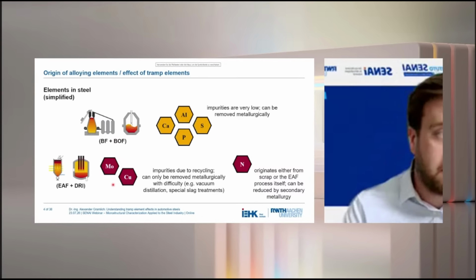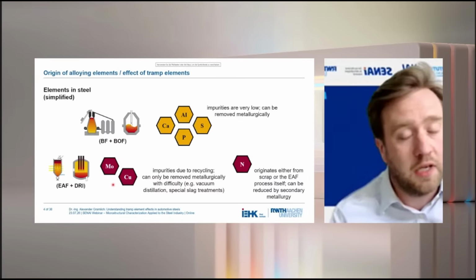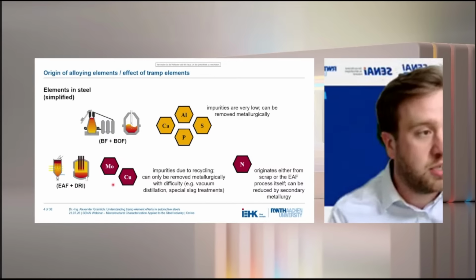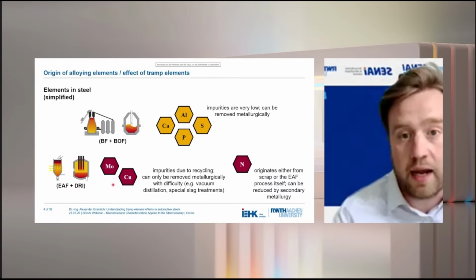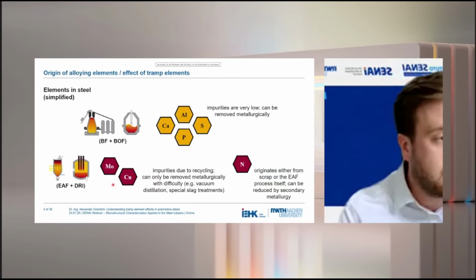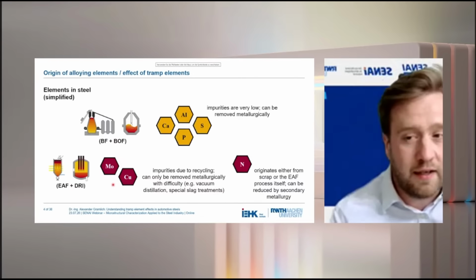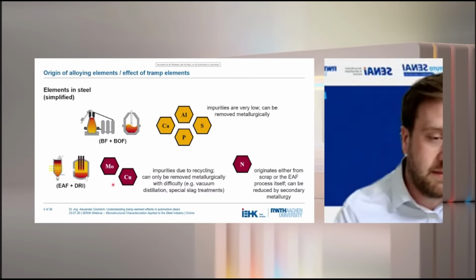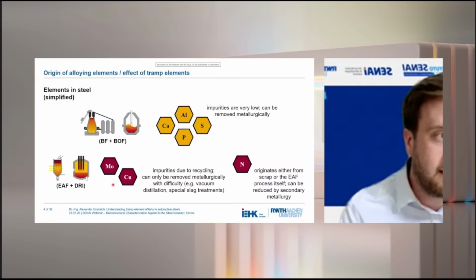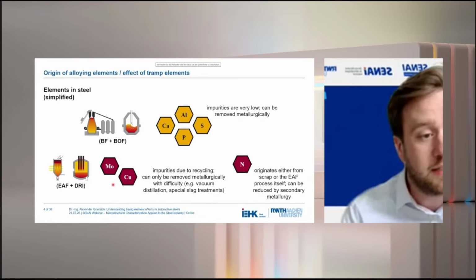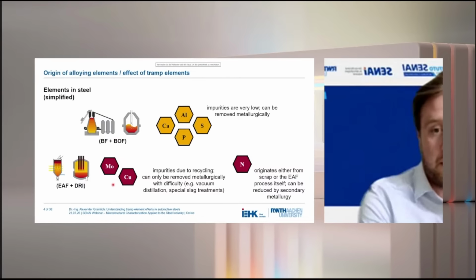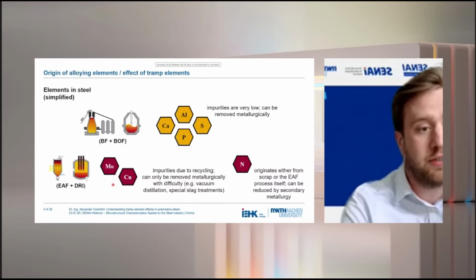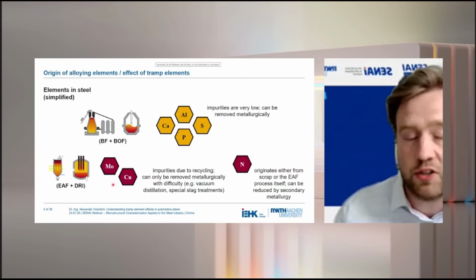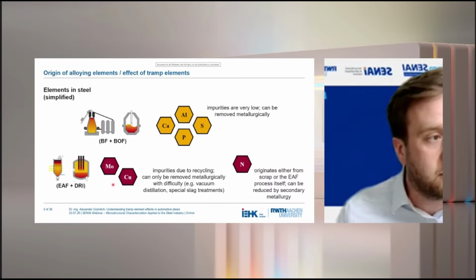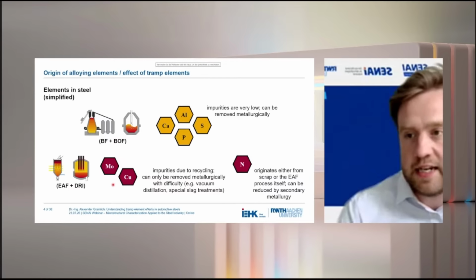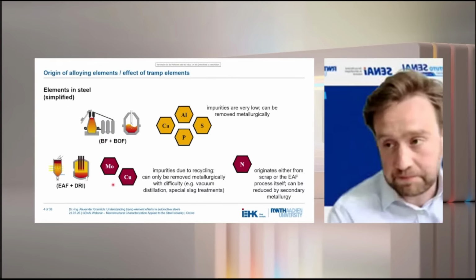Additionally, we are talking also about nitrogen nowadays in Europe because a lot of steel concepts, especially for the automotive industry, like bake hardening steels or interstitial free steels, are very dependent on having high cleanliness and especially low interstitials. And when we are now moving from a blast furnace-based steel production to an electric arc furnace-based steel production, these nitrogen levels are also increased and processes need to be adjusted more or less.